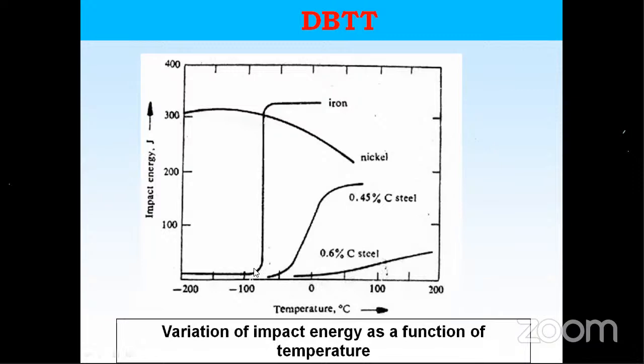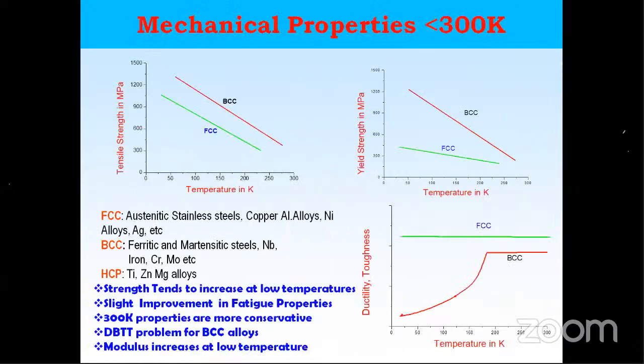That means it cannot take any dynamic loading. If you put iron or steel at a low temperature, even lower than minus 100 degrees centigrade, any dynamic or impact loading can break it. So we cannot use it. BCC material we never use at low temperature, but there are some exceptions.